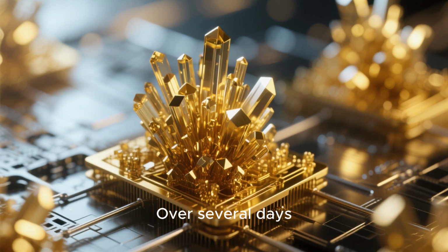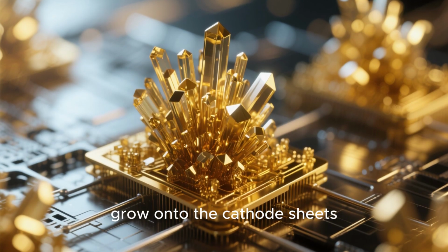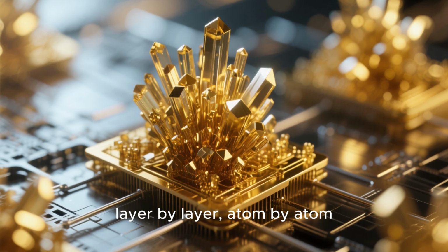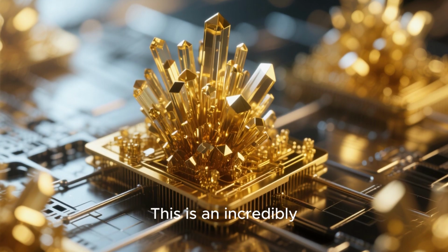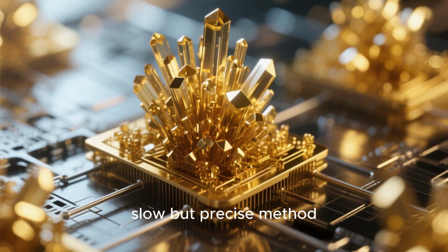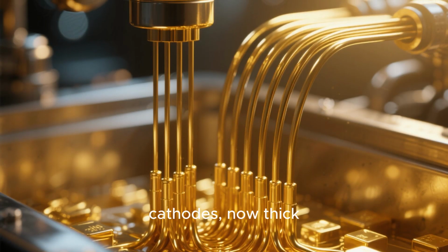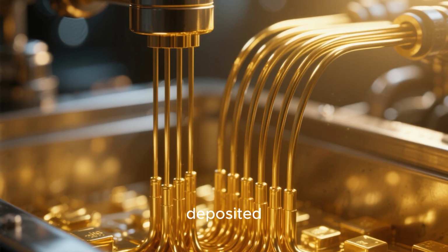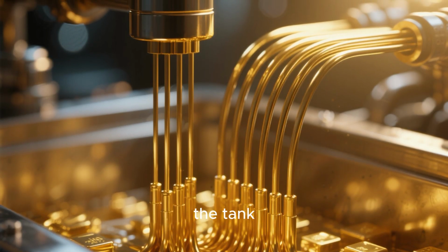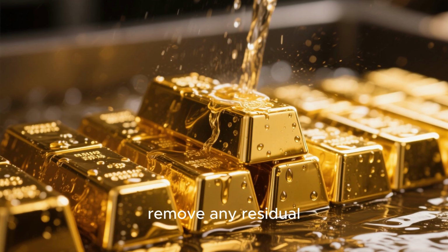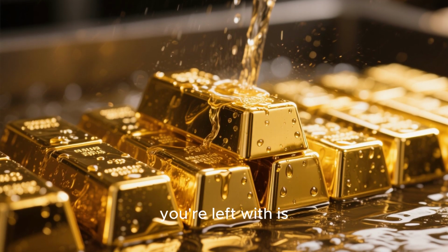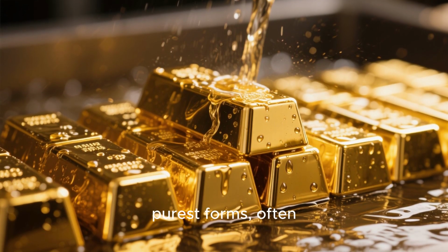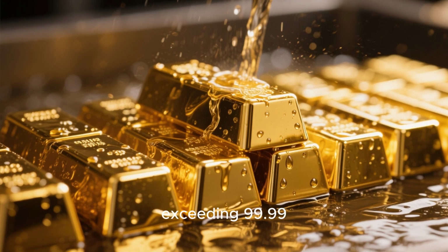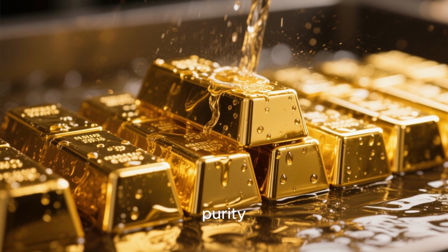Over several days, pure gold crystals grow onto the cathode sheets, layer by layer, atom by atom. This is an incredibly slow but precise method. When the process is complete, the cathodes, now thick with freshly deposited, ultra-pure gold, are removed from the tank. They are washed to remove any residual acid, and what you're left with is gold in one of its purest forms, often exceeding 99.99% purity.